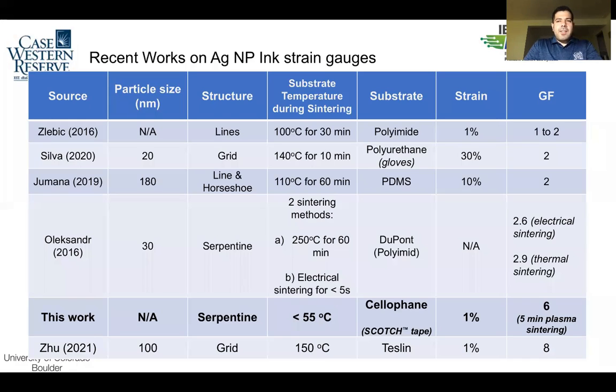Here in this table, it lists a summary of recent works on silver nanoparticle ink. I'm making this comparison because silver nanoparticle has been widely used in making temperature sensors or strain gauges. So if you look at this table, it's sorted on the gauge factor value from lowest to highest. The highest one is done by Zhu group, had a gauge factor of equal to 8, while in our work, we report a gauge factor equal to 6. That's the second highest in this comparison, while the other works have a gauge factor from 1 to 3.